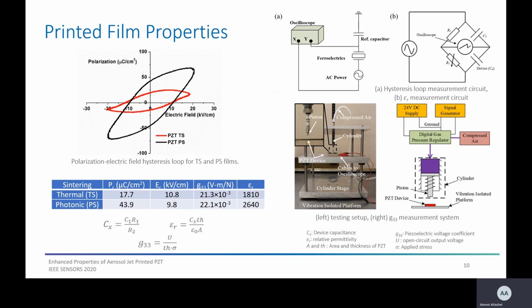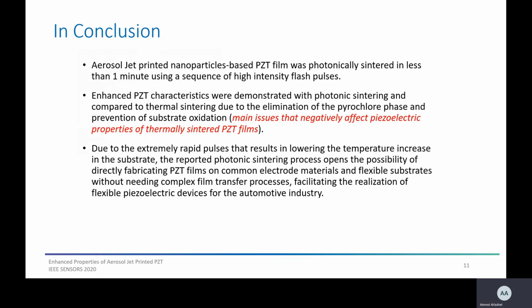So in conclusion, aerosol jet printing of nanoparticle-based PZT with photonic sintering has demonstrated superior performance in a very limited time with ambient environment processing. The enhanced characteristics were demonstrated with the photonic sintering compared to the thermal sintering process. The two main issues, oxidation and the pyrochlore phases, seem to be eliminated, and they negatively affect piezoelectric properties for the thermally sintered film.